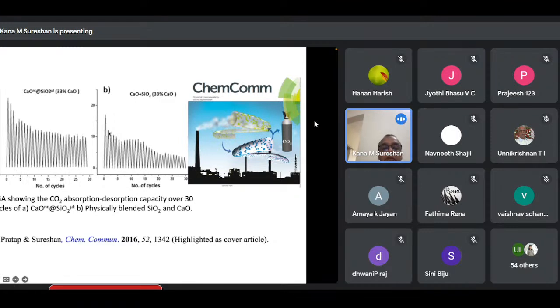At first itself, it goes to sintering, actually, 10%. Then after 30 cycles, you can see this is the 5 mark. It's much less than 5, about 3%. This is about 12 to 13%. So we have in principle shown that our use of gelator to make nanocrystals of calcium oxide would prevent this sintering, and we can absorb carbon dioxide from the atmosphere.